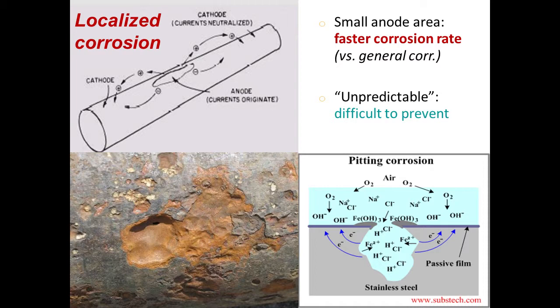Well, 10 is just an order of magnitude, but it's highly difficult to predict how fast it's exactly corroding. That's the same issue with chloride-induced rebar corrosion. There's no way you can simply design rebar to be thicker and avoid that problem. You still have that problem because that area corrodes really fast, and then it could have structural failure or other consequences. So when it comes to pitting corrosion, undercoating corrosion or under-deposit corrosion, another issue is you have areas where oxygen is having a difficult time getting in, and somehow the local chemical environment has changed. The pH drops, so that local environment becomes really acidic.